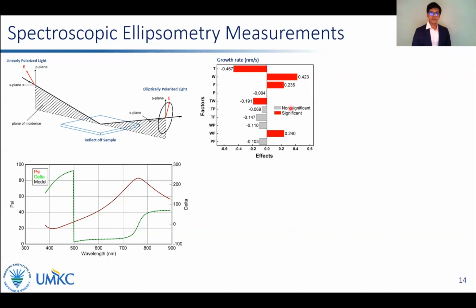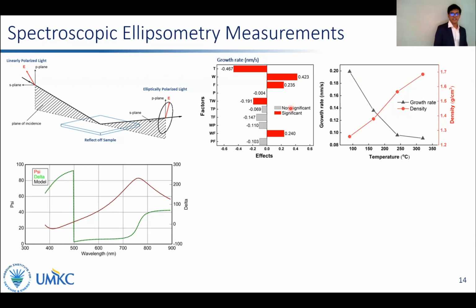The temperature and plasma power were found to be the most significant parameters, and we deposited a series of thin films at different substrate temperatures to understand their effect in detail.